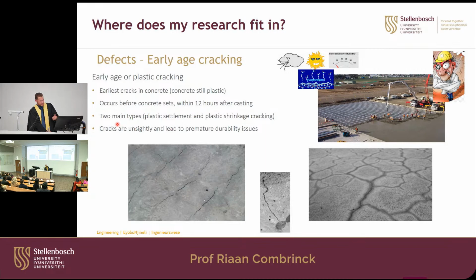And there's two main types. There's plastic settlement, which is when you have reinforcing steel, and if there's no reinforcing steel, you can get cracks like this. You can see the crack that you get with this early age cracking goes directly to your reinforcing steel, if there is reinforcing steel. So it's really premature durability issues early on in the life of the concrete.